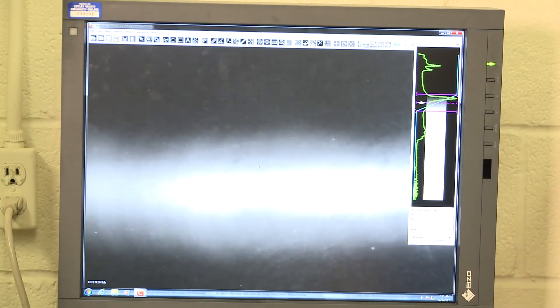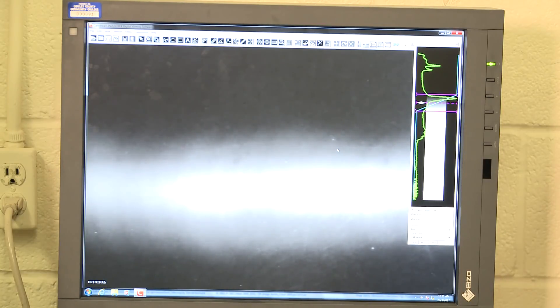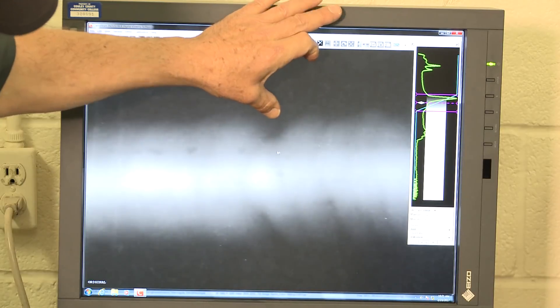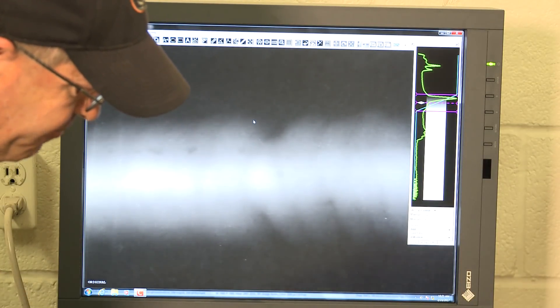A dark area would indicate a void. If it was really round, we would say it's possibly porosity. Generally, the way we view these radiographs is: if it's a darker area, it is something less dense in the metal — meaning there's less metal there. If it's something lighter, that means there's more metal there. So if you're doing TIG or you get your MIG gun in the end of the weld pool, those are going to show up as a more dense, lighter color area. As we scroll through, you can see there are several places along this weld where these dense areas occur. On the outside here it almost looks like a V or a U — a good road map to see where we are inside the weld. It looks like a restart.